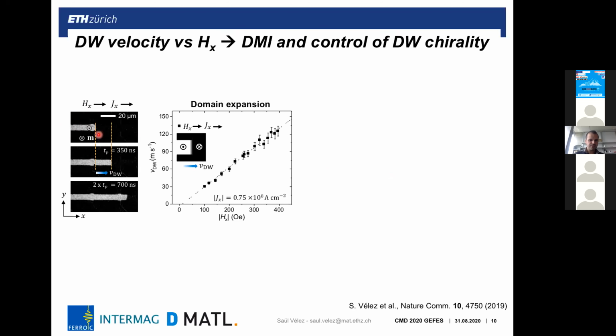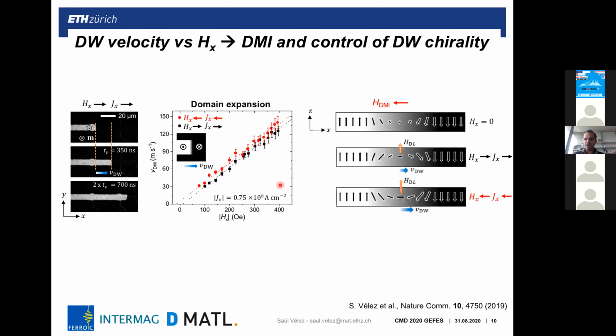But still, we could drive domain walls, as I'm showing here. If we have a domain like the one shown here, we can apply a pulse and drive domain walls from left to right, measuring the displacement as a function of the pulse length. So we can extract the domain wall velocity. If we do this for different magnetic fields, we see a linear trend as expected. And when we measure the other configuration of magnetic field and current, we see that we have a shift, telling us that this shift is related to the internal Dzyaloshinskii-Moriya interaction that we still have in this system, which is partially quenched with the platinum top layer.